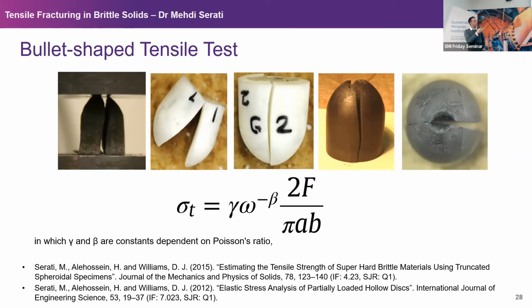So basically, we proved that yet another method to measure the tensile strength is by loading a bullet-shaped sample, which might seem odd because it's very difficult to prepare a rock in this shape. It's not designed for rock in this specific test, but rather for a very strong type of material like diamond that at the time we were dealing with during this smart cut project.